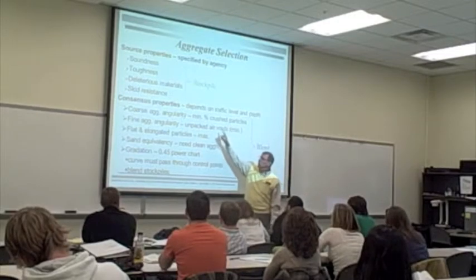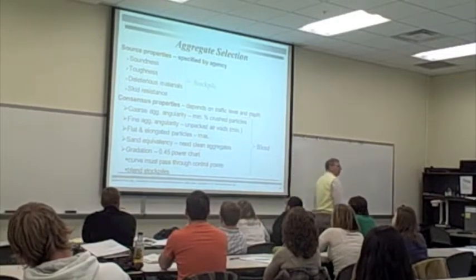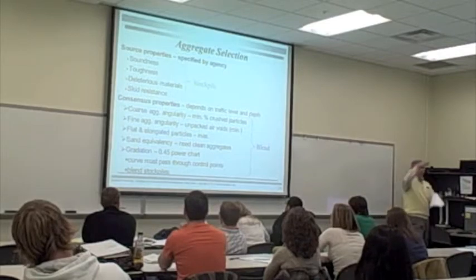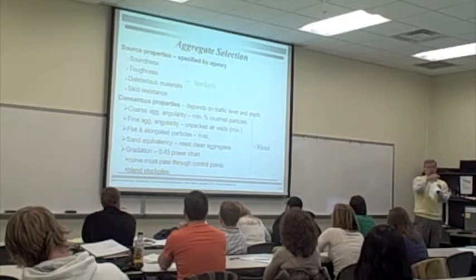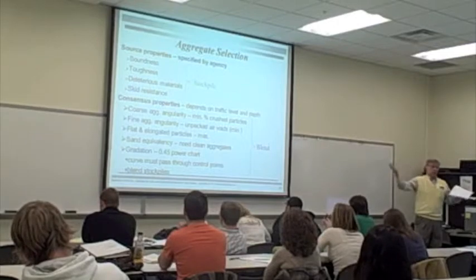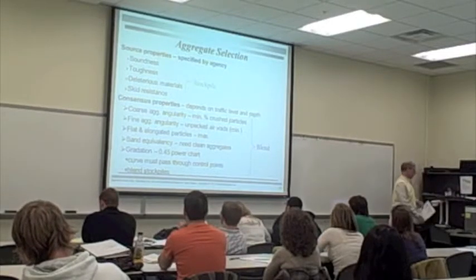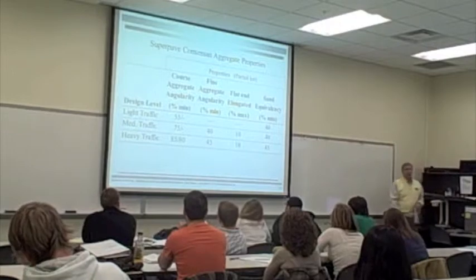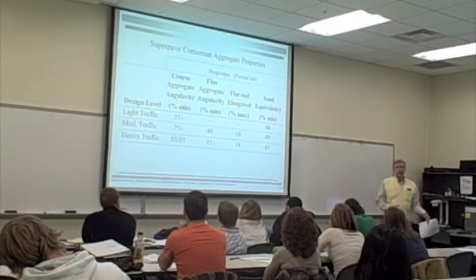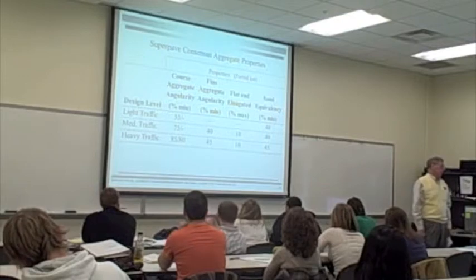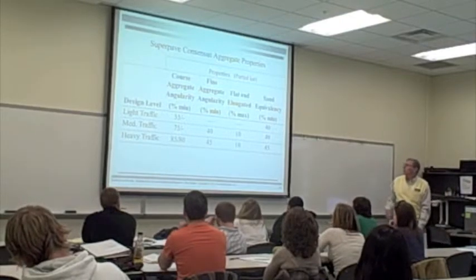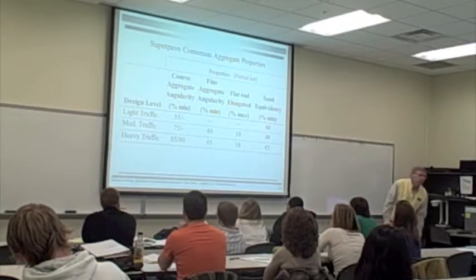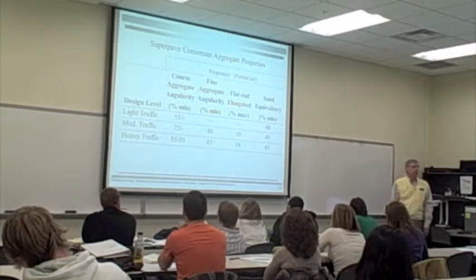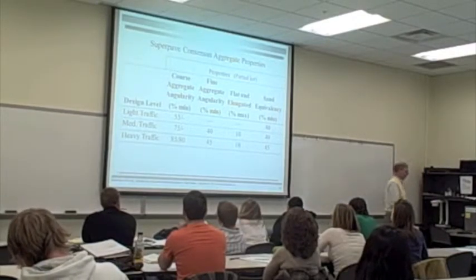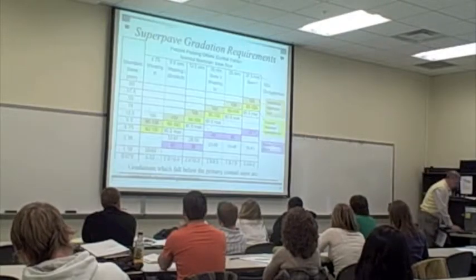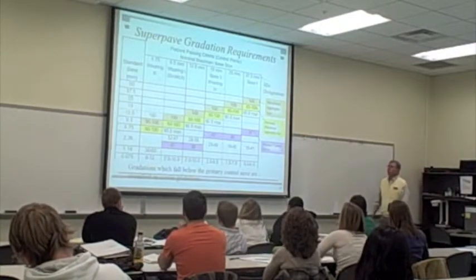Of these, the hardest one to achieve is the fine aggregate angularity, but that's what gives us the stability of the mix. You think you've got the big rocks there, you put some sand, which is basically very round, it's going to act like ball bearings, you're not going to have a stable mix. Okay? So you have a test, and the test is meaningless unless you know what a bad number is, right? So fine aggregate angularity of 45, if we're doing heavy traffic, that's the minimum. That's a hard one to reach. We're only talking about national stuff right now. West Virginia's tuned this up a little bit.